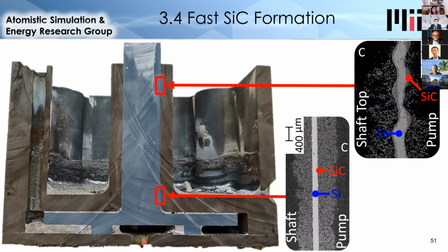And so we see that in this test, the pump shaft got stuck after rotating for a few minutes. And when I look into it with a scanning electron microscope, at the bottom of the sleeve, where it was lowered slowly into the silicon, we see a thick silicon layer between the two components, the pump body and the rotating shaft. And so this is what we would expect to see, and this is good. On the other hand, at the top of the pump, where silicon was introduced quickly because the pump speed was increased and silicon was forced up this passage, the layer is much thicker, the surfaces are very rough, and silicon carbide actually connects between the two components in several areas. And so this very clearly shows the difference between slow and fast silicon carbide formation.